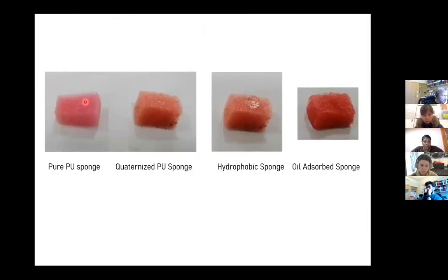And this is the polyurethane sponge which we have used, and it is functionalized with our organogel. So all the pores, the linings of the pores, are coated with this organogel. So this gel, which initially absorbs water, now turns hydrophobic. And this is a fully oil soaked sponge. And when we just squeeze it, you can recover back the oil. Now we would like to try this for soot as well as for dyes.